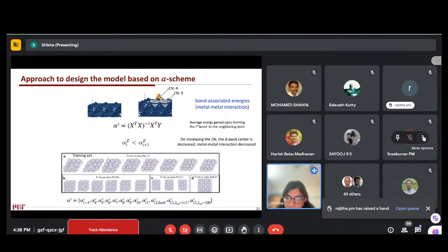So that way, we have the equation, we have the parameters, we have the matrix. The matrix would be the counting of the coordination number when we add the atoms, and our Y is the array of the binding energy from the DFT. So by performing a certain number of DFT calculations, we can predict the metal interaction energies.